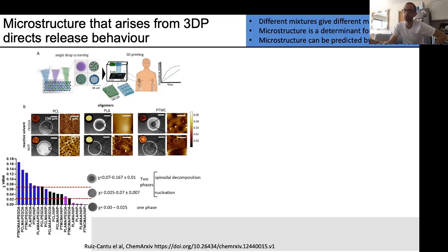So what we did was we performed a screen with various different combinations of our materials. So for example, on the top left, we've got polycaprolactone mixed with PEGDA, or we've got NVP and various different other core materials, polylactic acid, trimethylene carbonate, and ask the question, what kind of microstructures should we expect from that? And then we decided to back that with an analysis based on the Flory-Huggins interaction parameter, which gave us a really nice correlation between the kind of observations that we got and the interaction parameter values that we found.